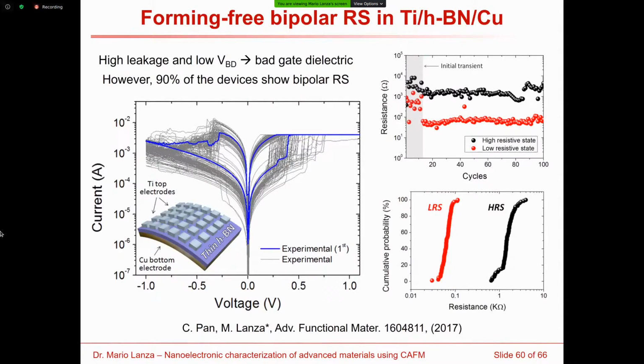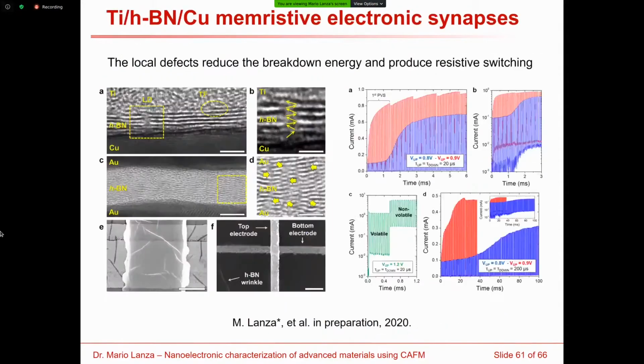So basically, we use this material to fabricate some electronic memristors that can fluctuate between the high resistive state and the low resistive state. And this can be used to store digital information. We published this work in Advanced Functional Materials, and after that, we also noticed that if you apply some specific electrical stresses, you can even induce some potentiation and depression in your material. So basically, you can use this dielectric as electronic synapse.